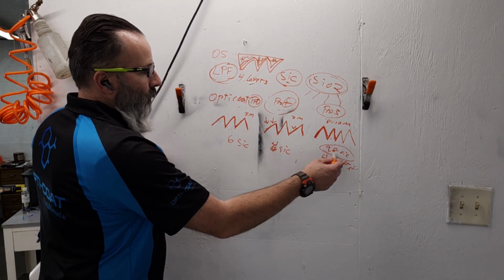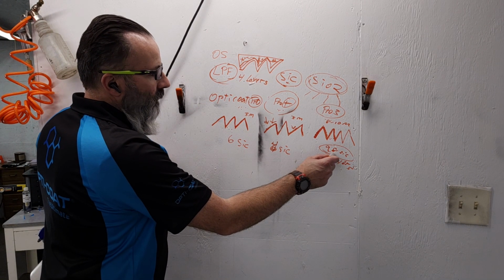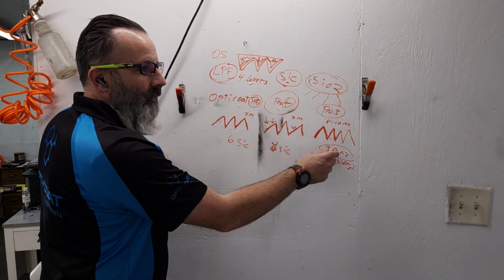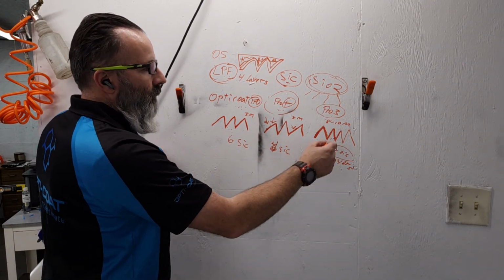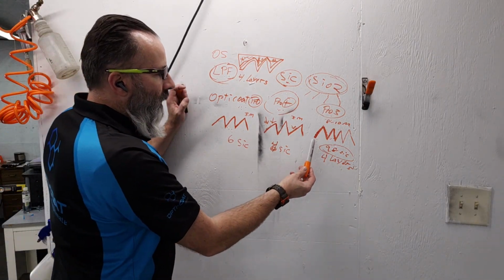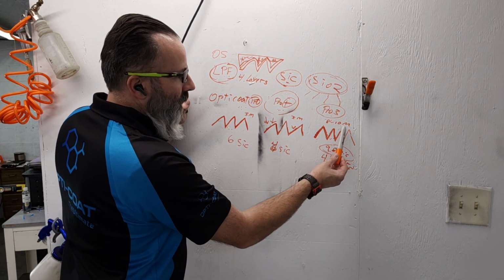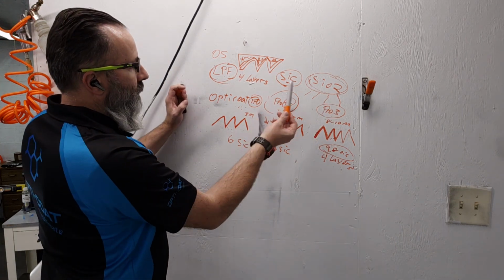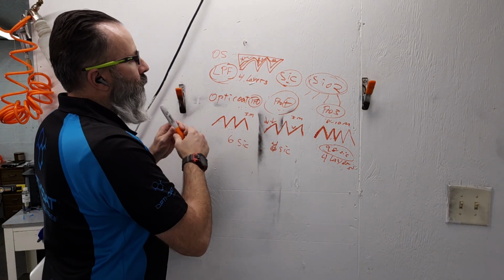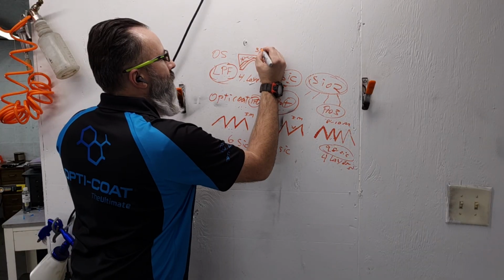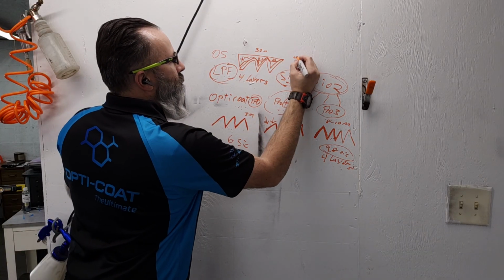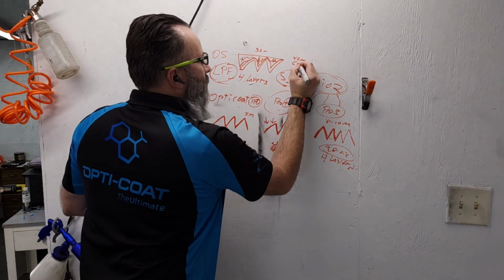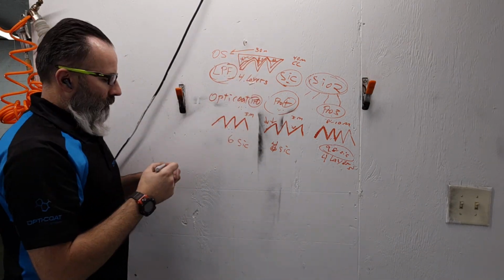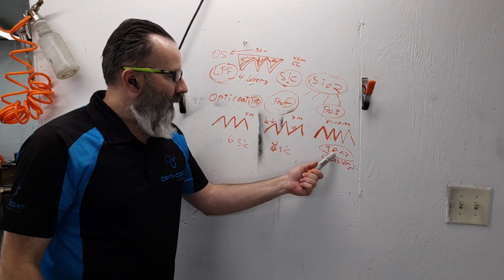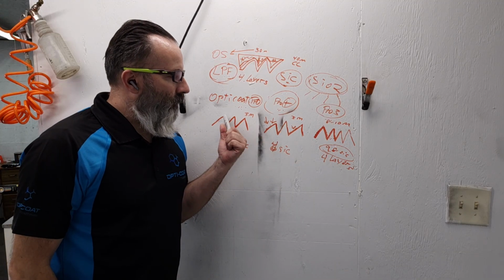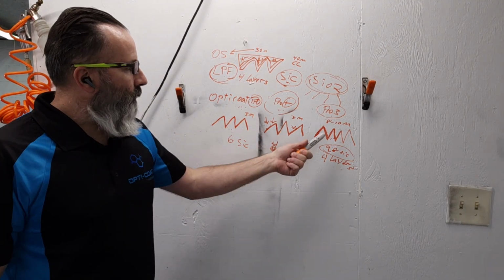So Pro 3 has as much silicon carbide as it could possibly have and still be categorized as a ceramic coating. And why is it only a ceramic coating? Because it's only about 8 to 10 microns compared to 40 microns of clear coat or 30 microns with LPF, Opti-Shield. Clear coat is 40 microns. So we can't categorize Pro 3 or Pro Plus or Pro as LPF because it's too thin.